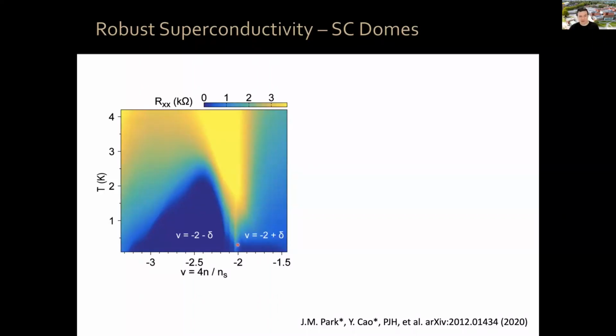This is the dome around 2 holes per moiré unit cell, okay? You have a big dome here and a much smaller dome here. We call this -2 minus delta. Delta means extra doping, okay? So this -2 plus delta, we're adding electrons. Here we're adding extra holes with respect to filling factor nu equals -2.